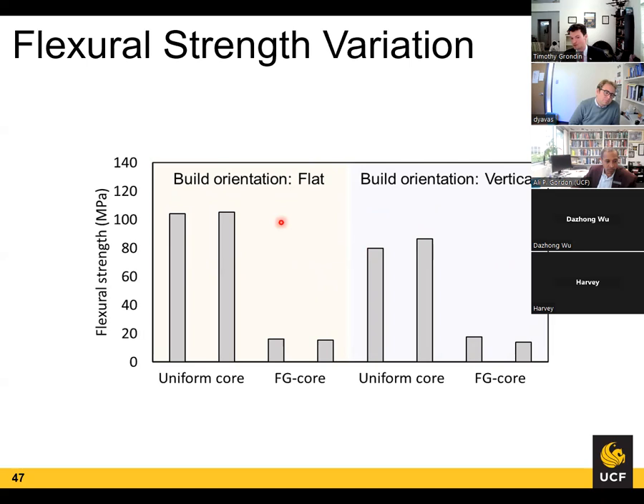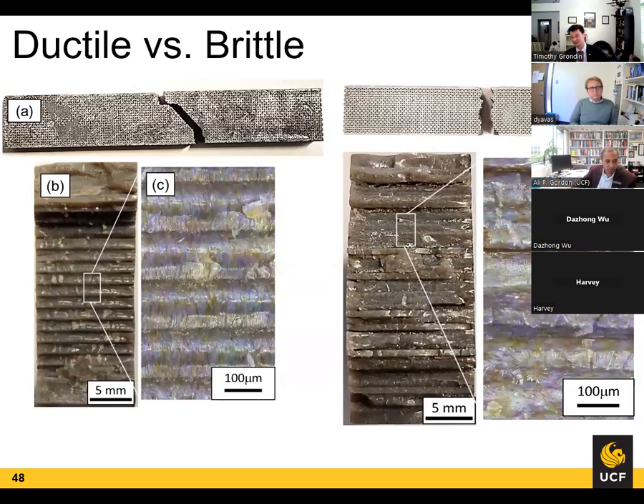Functionally graded core did come out weaker due to a failure mode transition, which we'll be able to show in some of the later pictures. But overall, in the constant density samples, we had a face yielding, where the faces of the actual core broke, or the faces actually broke by the core. And then in the functionally graded one, we had a core yielding due to core shear and then eventual core collapse from the compressive forces. So the shear strength drop at the neutral axis overall led to these results, but we also noticed a progressive failure, which led to secondary effects of energy absorption, which is awesome. We're going to investigate that in a little bit.